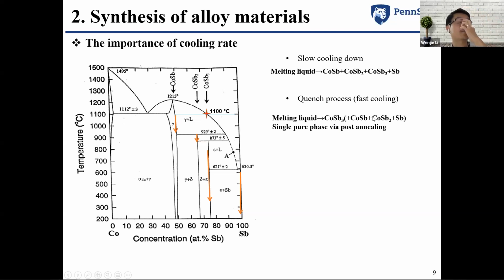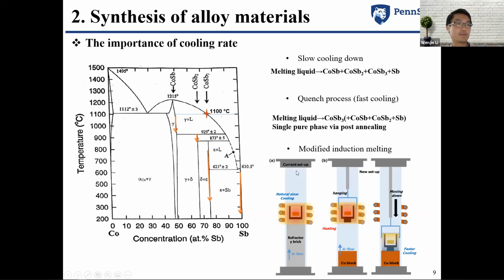Of course, because the cooling rate may still not be high enough, we still get some secondary phases, but we can remove them by post-annealing to achieve the single phase. Based on this quenching principle, in our lab we also modified our induction melting a little bit. This is how it looked originally, where we held the crucible using a refractory brick, and with the new design we hang the crucibles with wires and locate them at the heating region.